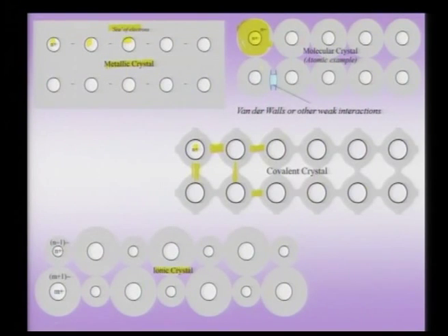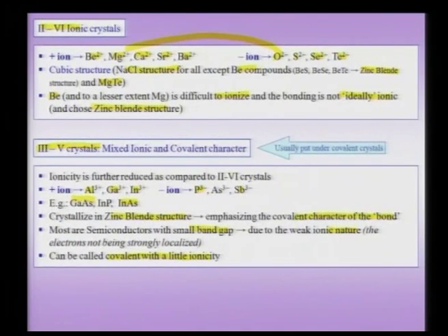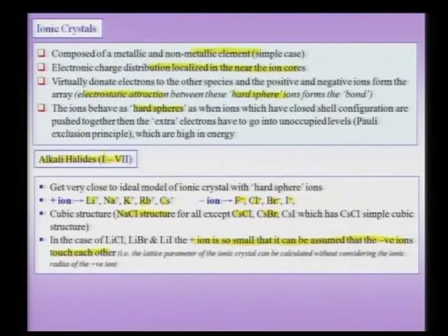Okay. I am not quite understanding what you mean by a soft sphere interaction, but let me guess what you mean. What we mean by a hard sphere interaction is what is said here in this slide. In other words, if I approximate my ion to be a hard sphere, that means that there is a region from which another ion cannot approach. So, when two ions are far away, it is purely an electrostatic attraction. But when it comes closer, it stays in attraction, but after a certain distance the repulsion goes to practically infinity. So, this is what I mean by a hard sphere repulsion.